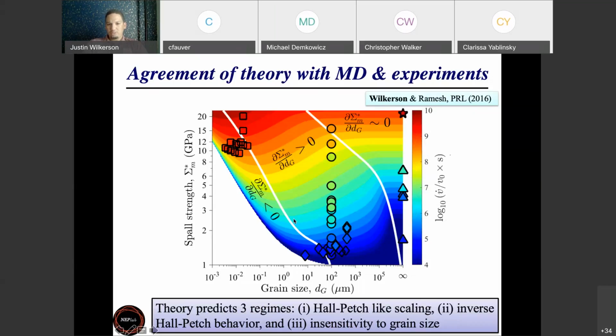In that case, you would see that you get the lowest spall strength at this grain size of 5 microns or so. And if I increase the grain size from there, I would get an enhancement of the spall strength. The spall strength goes up. So something like reverse of Hall-Petch effect. And if I go to the left from that bottom trough, then I get an increase in spall strength, something like the Hall-Petch effect.